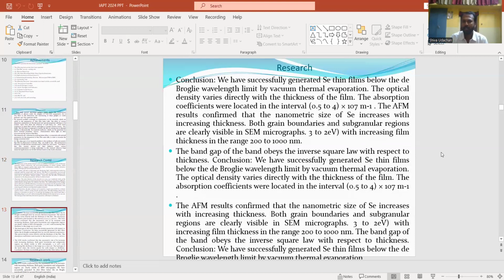Conclusion: we have successfully generated selenium thin films below the de Broglie wavelength limit by vacuum thermal evaporation. The optical density varies directly with the thickness of the film. The absorption coefficients were located in the interval of 0.5 to 4 × 10^7 per meter. The AFM results confirm that the nanometric size of selenium increases with increasing thickness. Both grain boundaries and subgranular regions are clearly visible in SEM micrographs.